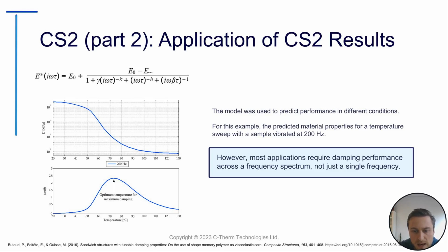What they're able to do now is model, for instance on the left here, the performance of a temperature sweep if the material was being excited at 200 hertz. What they could do essentially is determine the optimum temperature for maximum damping for a signal at 200 hertz. So if we consider something rotating at 200 hertz at around 75 degrees Celsius, that material would have maximum damping.